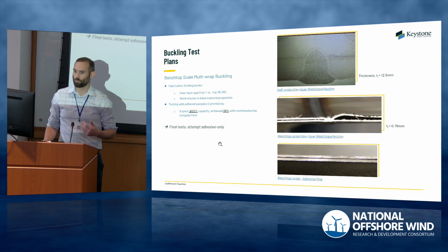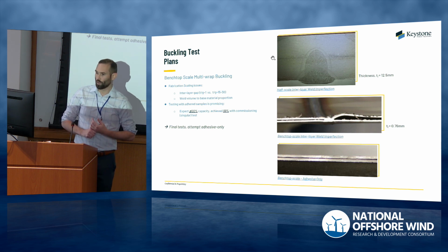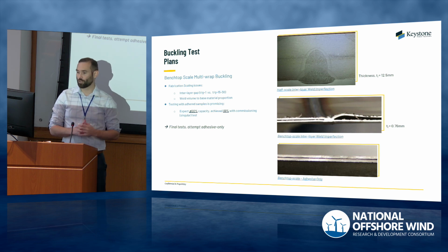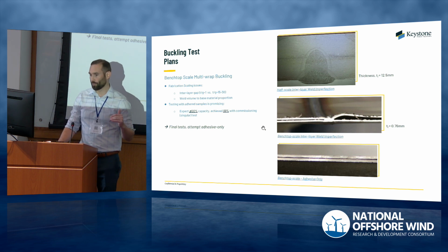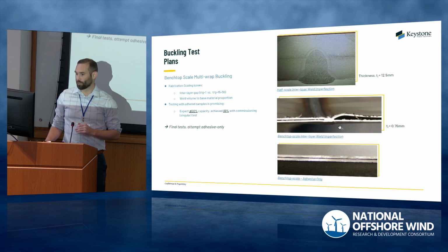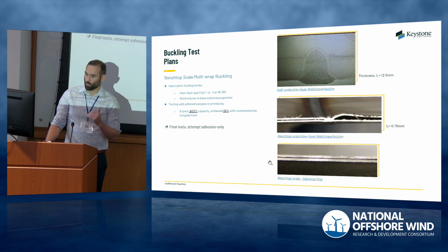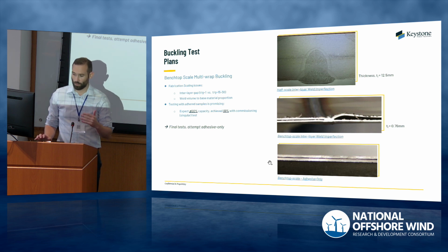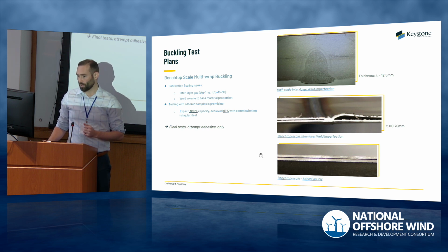And here I talk more about the small scale effects of fabrication. So this top image is from our weld development for fatigue testing, which I'll talk about next. And so these are 1/2-inch thick plates. You can see a gap exists between them. There's a two-pass weld, and you can see the heat affected zones, all that good stuff. But you can see the relatively high thickness to gap ratio, and you can see very little distortion between the layers. Whereas what we've seen on these small lab scale multi-layer samples is this very large weld bead relative to the wall thickness, and we're getting all these crazy shrinkage distortions. And then this bottom image is the unwelded and adhesive only sample, which is obviously not distorted at all.